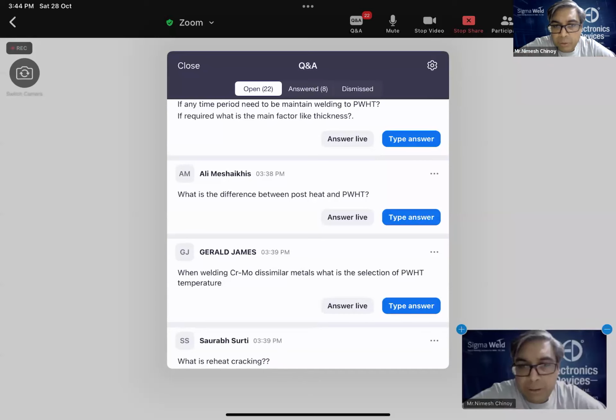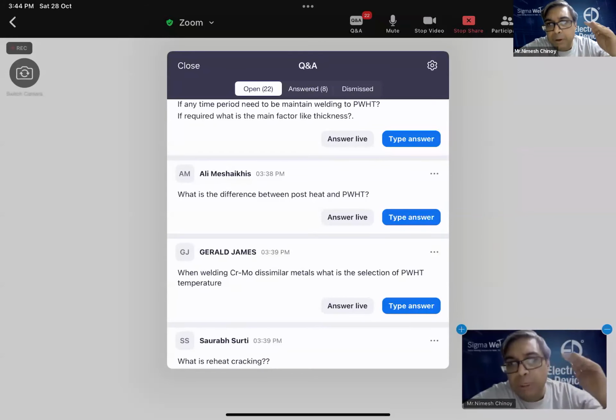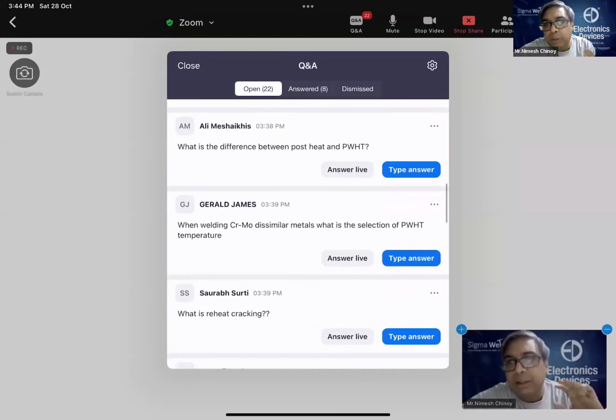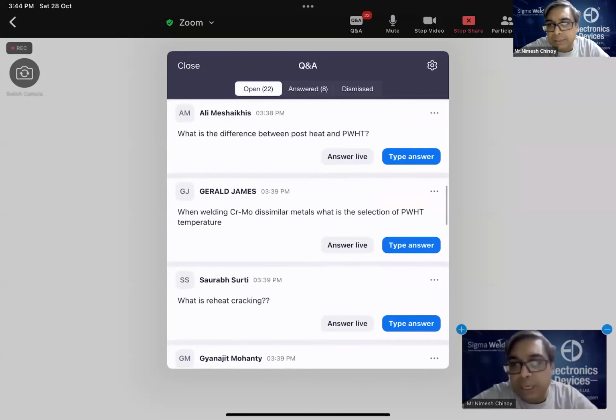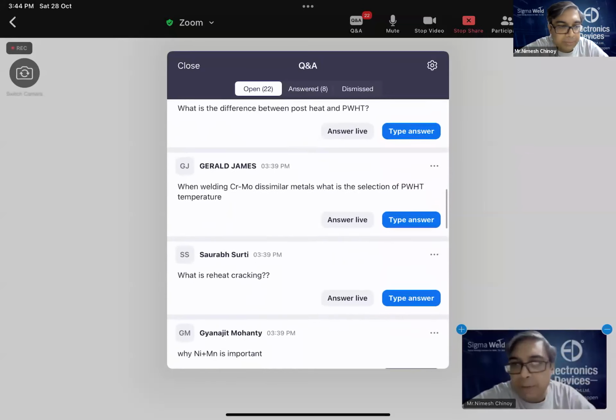In terms of P91 or other chrome moly variants, if you stop welding in between, you may have to take it up to DST or post heat, which is about 300 to 400 degrees depending on thickness and material. And in PWHT, you go all the way up to 560 or 600 degrees plus, and then you have to temper or normalize the steel. So these are two different processes. Post heat is only meant to take care of the hydrogen diffusion and DST in between the welding cycles. PWHT happens at the end of your entire welding when it's completed, just to add a fair bit to it. Yes.